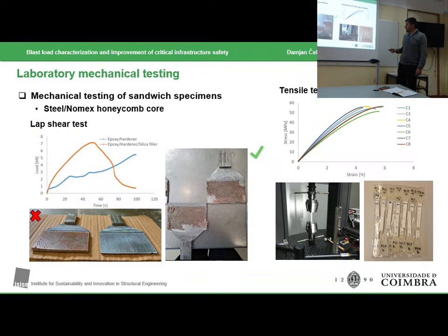Here, on the other hand, we tried several techniques to apply the epoxy to the steel surface. We tried rollers of different types, we tried using a spatula, we tried using pure epoxy, and we tried also increasing the roughness of the surface by sanding it. In the case of a very low viscosity epoxy, this is the failure that we got, and this is not satisfactory. In the lap shear test, only this kind of failure is acceptable, and we have reached this failure by adding